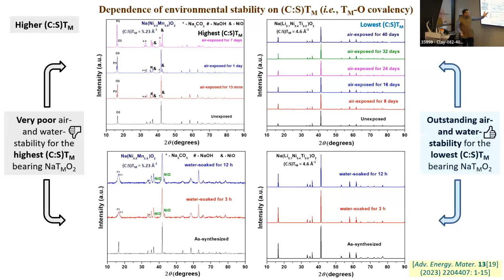The similar sequence of events happens when we dip it in water, just that it is faster. So after 3 hours, the structure is completely gone. Soak for 12 hours, it's gone. That is for the one with a high charge to size ratio of my cation combination in the transition metal layer, whereas this one is again not just air stable but also water stable.